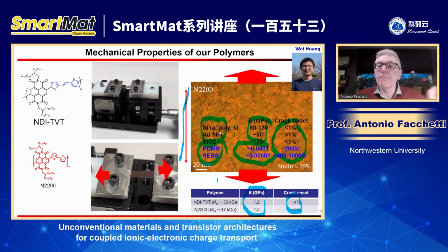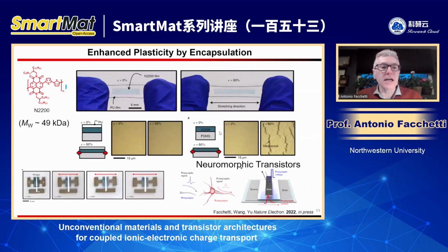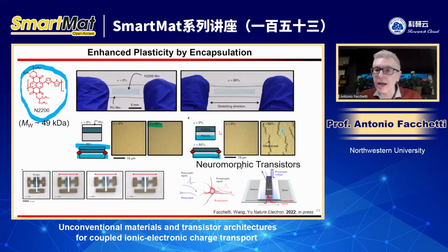So the question is, can we make this material more plastic, hopefully, or elastic? And what is interesting is we can take the same polymer. Instead of having the polymer on an elastomer, we embed the polymer between two elastomers. So this is exactly the same polymer, N2200, but here it is only on SEBS, and here it is covered with polyurethane. When you do that, you can stretch the same film 50%, there is no crack. Instead, if the polymer is not embedded, the crack occurs at much lower strain, about 3%.